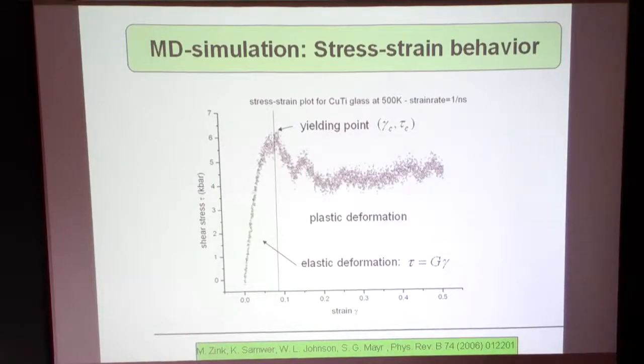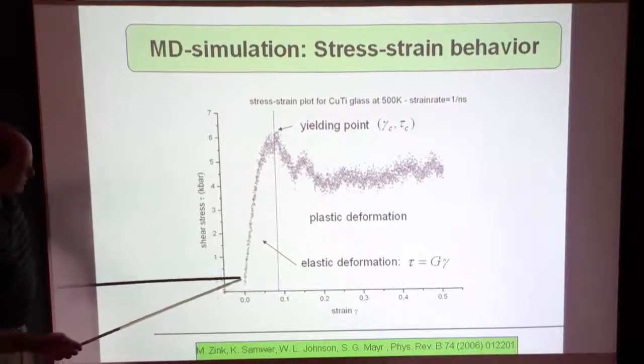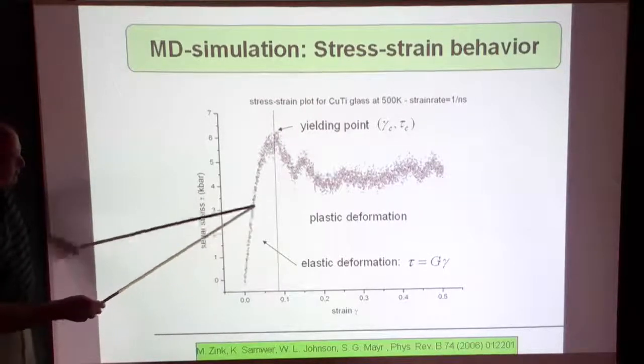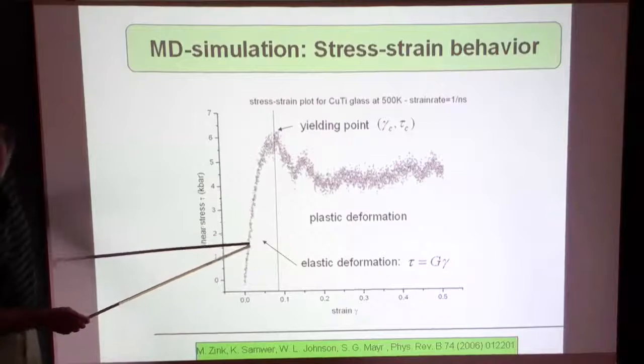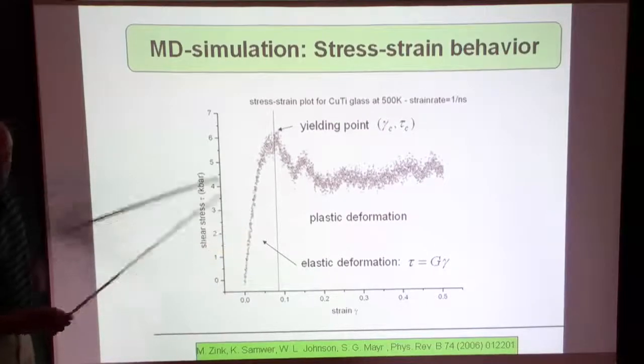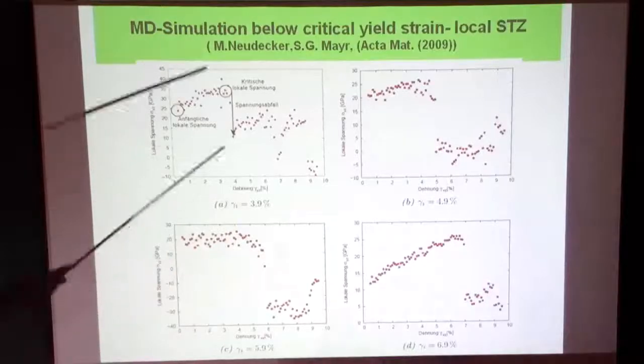To answer your question correctly, we cannot say whether this comes from the beta process or from the alpha process. We have only 50 nanometers resolution, and I can give you a number of how many plastic events, STZs, must happen before such a length change takes place. We're doing it also now for the MD simulation, getting statistics in these so-called plastic regimes, and we find many events. Stefan Meyer did it already some years ago.